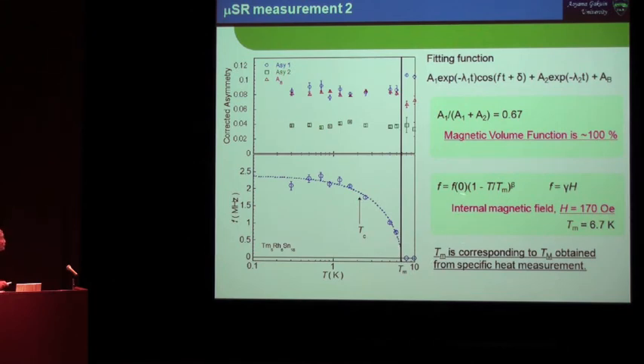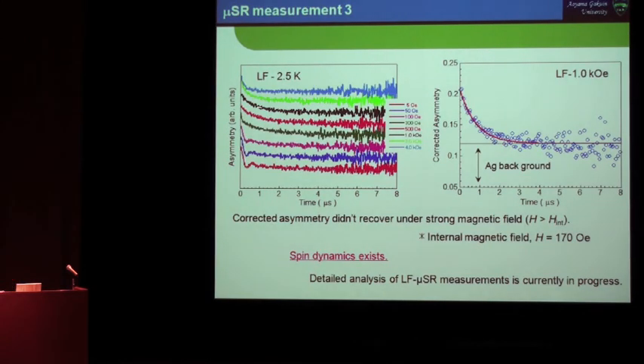However, this magnetism is probably not a long-range order, but some short-range order, cluster-size short-range order. This is a LF-corrected asymmetry, which would recover under strong magnetic field, but it does not. Probably this behavior shows that spin dynamics are existing. Detailed analysis is now in progress.